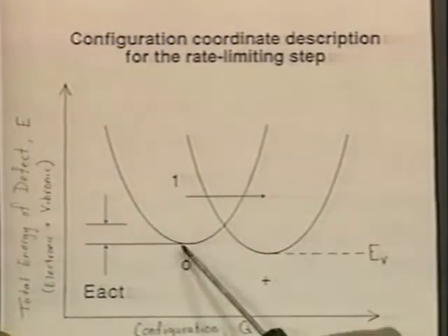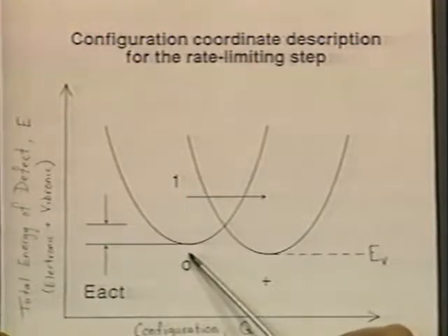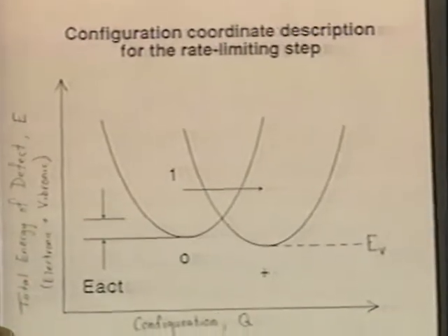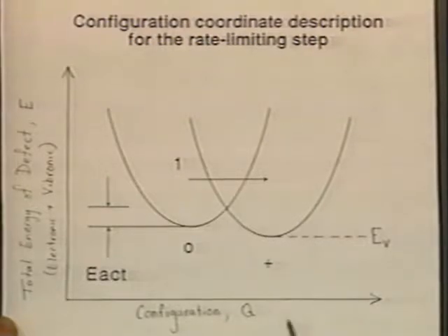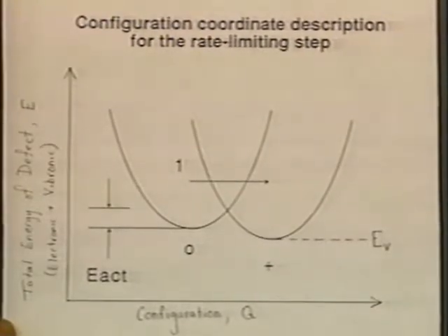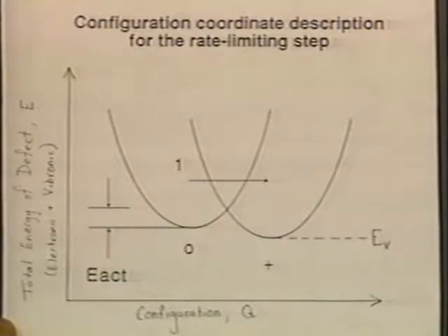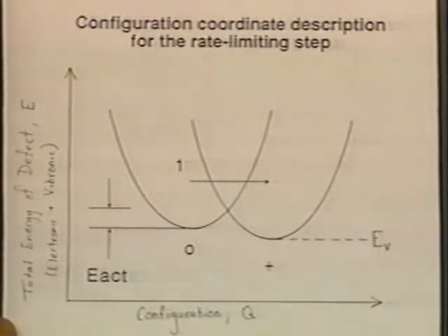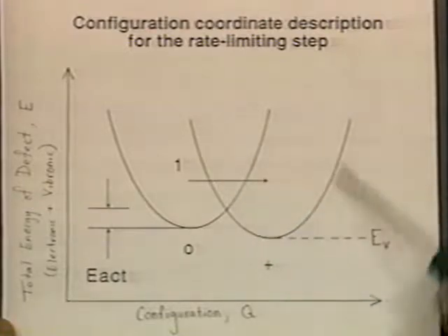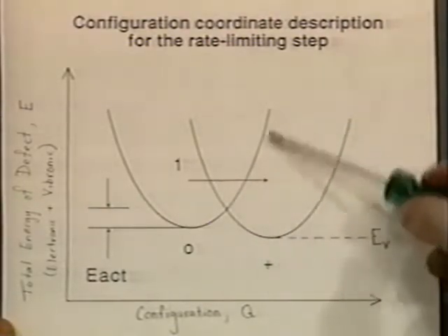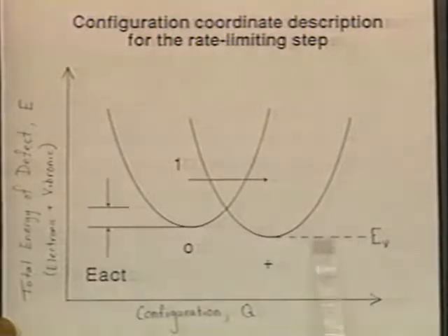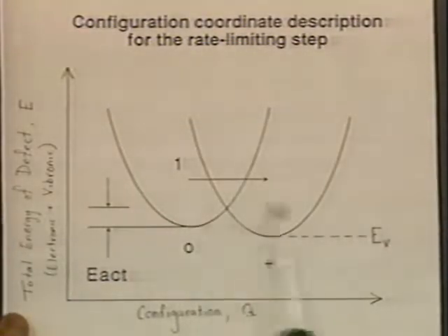Now what it does is it becomes a defect when it makes a configuration change. This is the configuration coordinate here. It makes a configuration change which may or may not be accompanied by a change in charge state. In this case, I believe it would have to be accompanied by a change in charge state and make it a positive charge. So you have a new harmonic oscillator, a new relative electronic energy, and you can reference that to the valence band. In that case, you would say what you're doing is you're capturing a hole. You've got an electron going to the silicon valence band, a hole coming into the defect. And so what you do is make a transition.